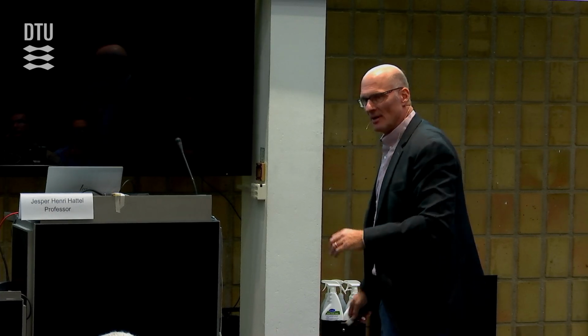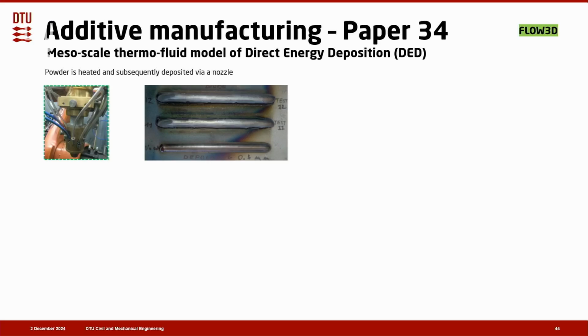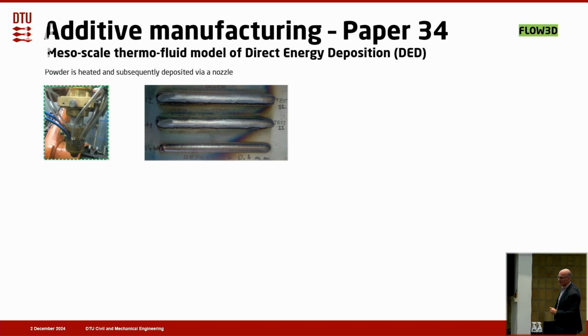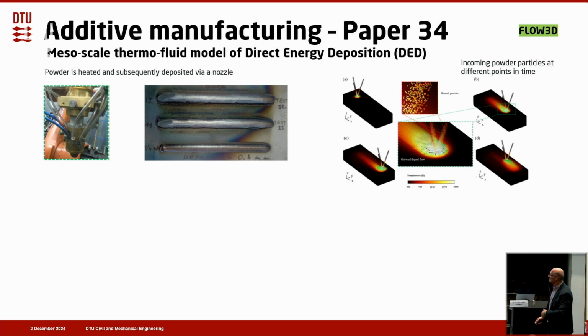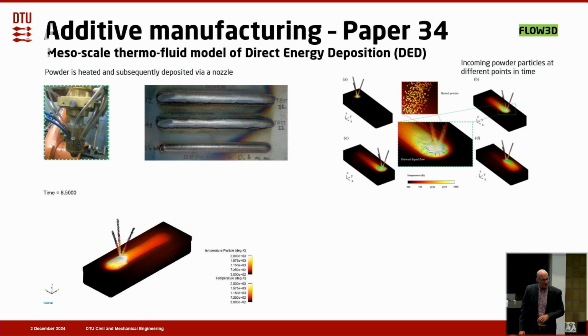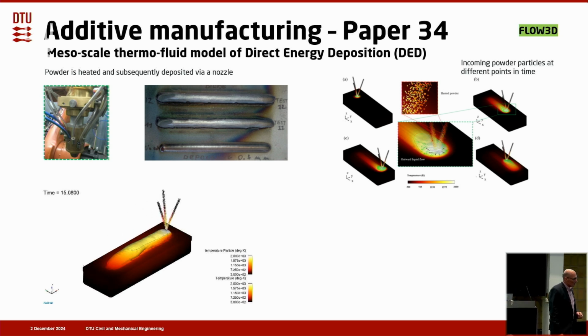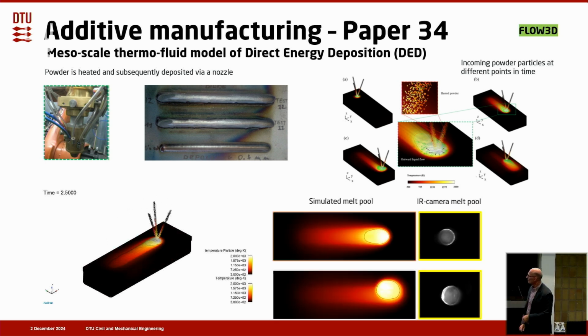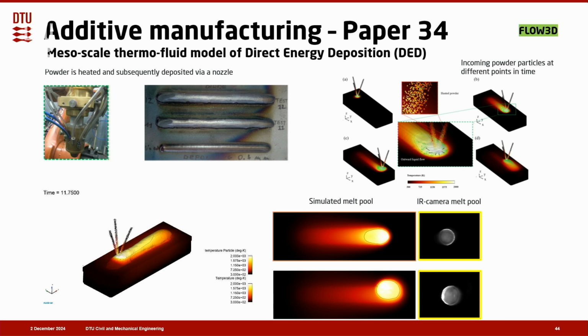And then the final paper, I can assure you, so there's not that much left, paper 34. There we did a mesoscale thermofluid model of direct energy deposition, a somewhat other additive manufacturing process. You see here the incoming powder particles at different points in time. And this is actually a simulation of that from our model, where you see the dynamics of the process. These are pictures of the simulated melt pool. This is the infrared camera of the same.